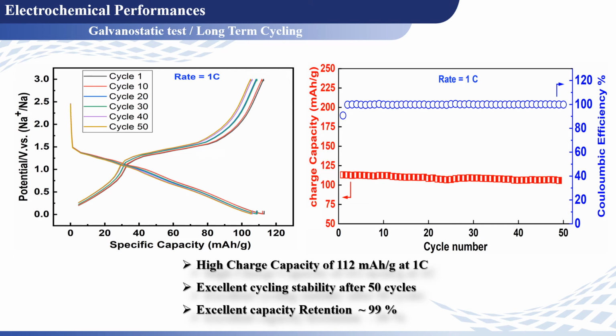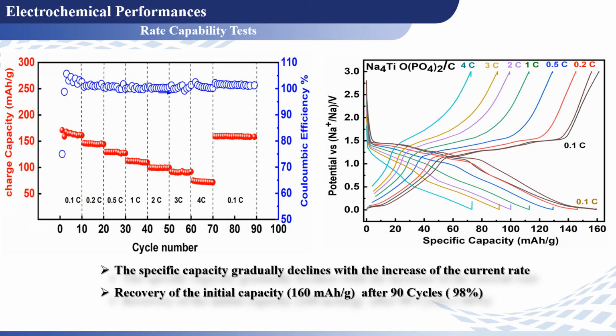After that, we tested our material by increasing the rate up to 1C during 50 cycles, and it maintained a high charge capacity of about 112 mAh per gram, and excellent cycling stability and capacity retention approaching 99%. More than that, the material exhibits excellent rate capability performances, even if the current rate has been increased to its highest value. Moreover, when the current density returns to 0.1 C, our material recovers the same initial capacity of about 160 mAh per gram.